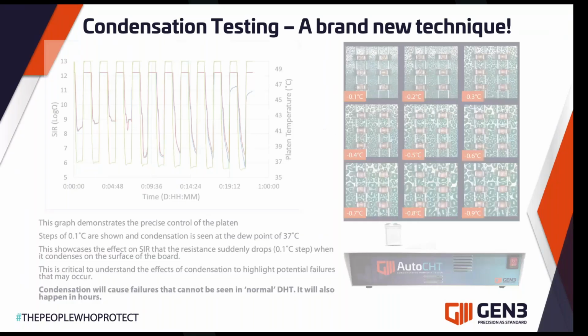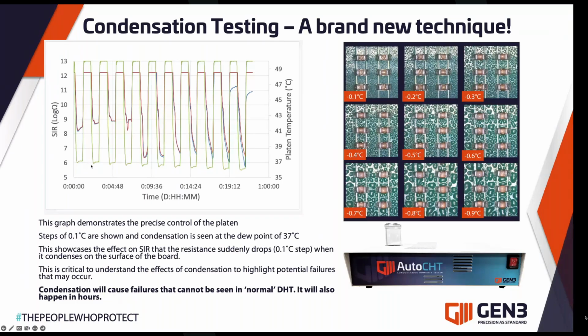Going forwards with condensation, this graph in the top left is showcasing the control. Each green line you see here is a step down in temperature of 0.1 of a degree. What we're looking at is a dew point at 37 degrees, and we're measuring on these red and blue lines what the resistance is. When we get to 37 degrees, there's a very, very thin layer, and we can start to see some resistance breakdowns. 0.1 of a degree later, bang, we see resistance drop. So this showcases the effects of condensation on the board and the impacts it can have. The fact that we can now see this at 0.1 of a degree differences showcases the effects that can occur. This is critical to understand the effects of condensation and can highlight potential failures that may occur. A very important statement is that condensation will cause failures that cannot be seen in normal damp heat testing. It will also happen in hours.